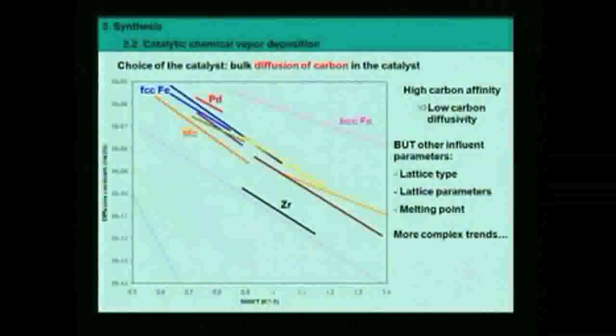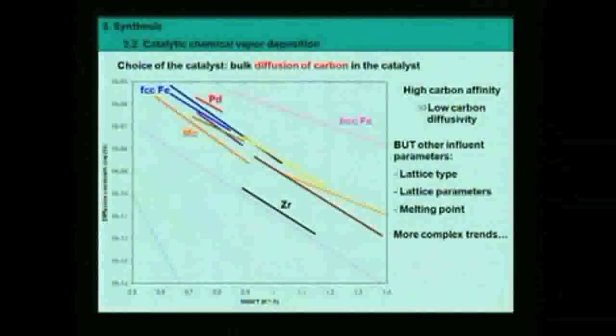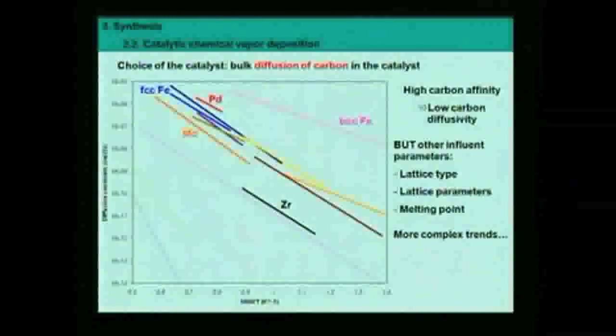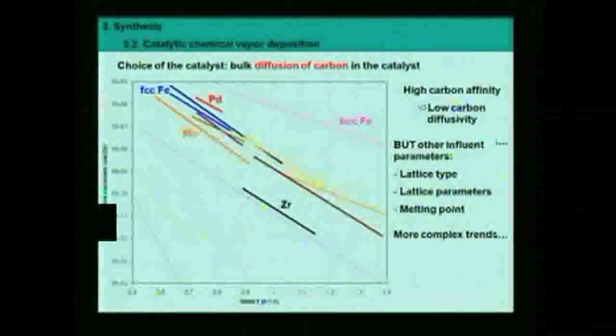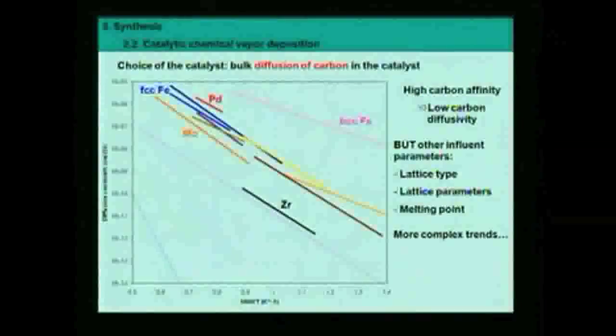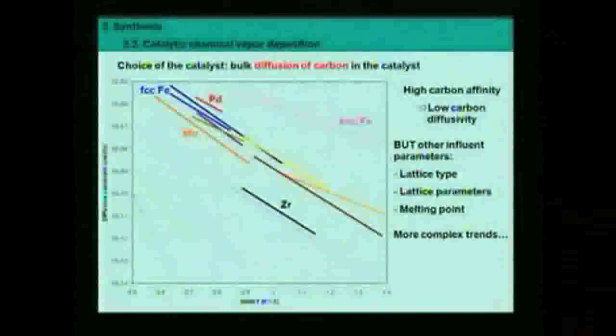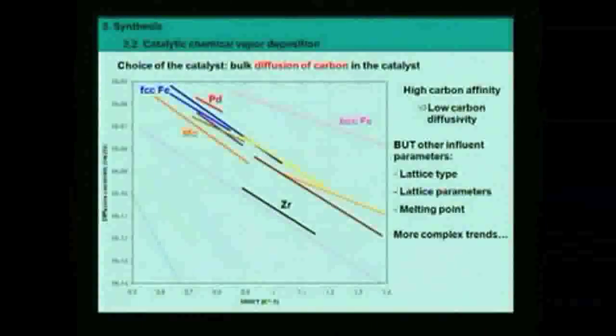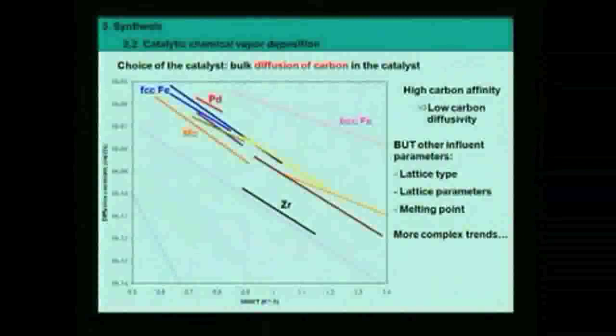Depending on the geometry of this lattice, depending on the size of the matrix atoms, depending on the size to go from one interstitial site to another, depending on the flexibility of this matrix. Are we close to the melting point, or are we very far from the melting point? These will give you an idea of how flexible the lattice is. Okay, so diffusivity is not just a question of chemical interaction. It's also a question about the geometry, the type of matrix the atoms have to go through. Okay, so it makes things more complex, especially because different metals have different crystal structures, different crystal lattices.